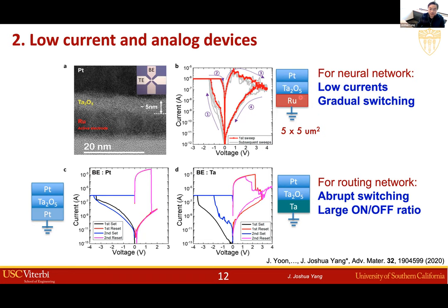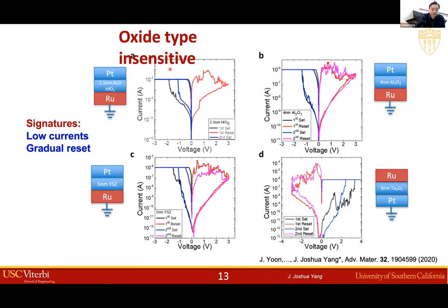And fortunately, we find that by replacing one of the electrode materials, from either platinum or tantalum to ruthenium, the device suddenly changes switching behavior, with very gradual on switching, gradual off switching, and also the current level is reduced by two orders of magnitude. So this is more suitable for certain applications, and we wanted to understand what's going on. Is this related to ruthenium?